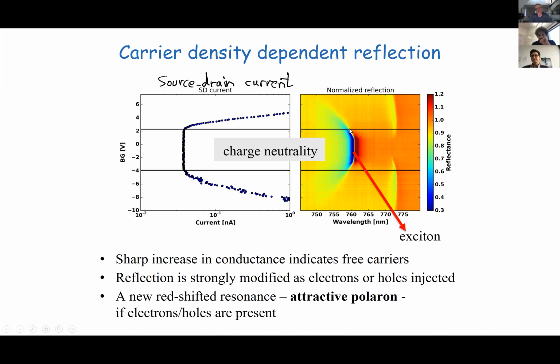Okay, now the interesting physics happens as we increase the voltage and start doping electrons. What we then see is that the exciton line shifts to the blue, and there's a new resonance that emerges on the red side and picks up oscillator strength. The same happens if you try to hole dope by reducing the gate voltage. And concurrently, we see that there is a source drain current that starts to run through the system, as a consequence of the presence of electrons for positive voltages and holes for negative voltages. Now, the new resonance that appears, which actually starts out at the trion energy, is what we describe, borrowing from the atomic physics community, as the attractive polaron.